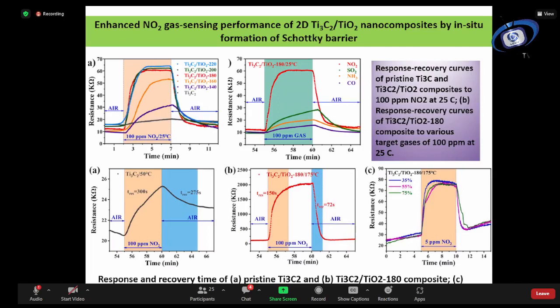So we can see there is a time of recovery and time of response in figure A at the bottom. The response time and the recovery time are very large, 300 seconds and 275 seconds. As I said in my initial two slides, all parameters cannot be satisfied at the same time. So we try to control some parameters and then get a specific output for a specific sample. And in figure B, you can see it has been decreased to 150 seconds and 72 seconds. Of course, this recovery time is very good, not that bad, although in the recent sample we have achieved a recovery time of about 10 seconds. So that is a very sharp recovery time for that one.